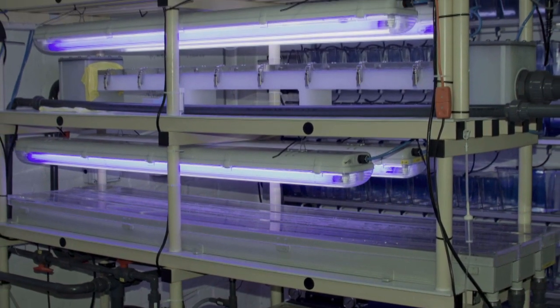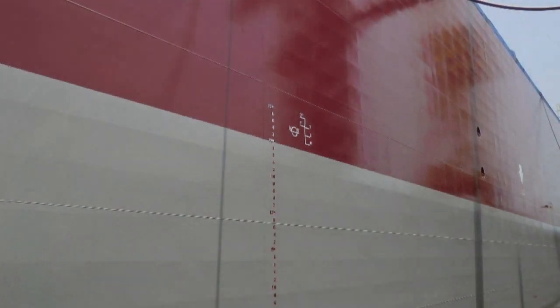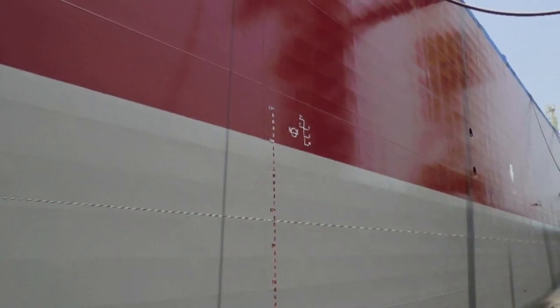We have people in different locations around the world — in Singapore, in China, in Dubai — the major yards for applying release-type products. We have marine biologists on site. We do bioassay testing, which involves growing different species of fouling on panels in the lab and testing settlement and release. We've scaled that all the way up to test patching — small test patches of around 25 square metres up to full vessels where we might apply 3,000 square metres and then measure the performance.